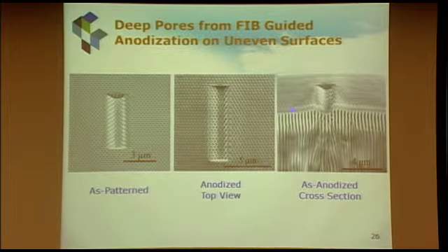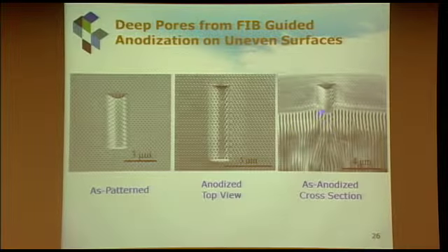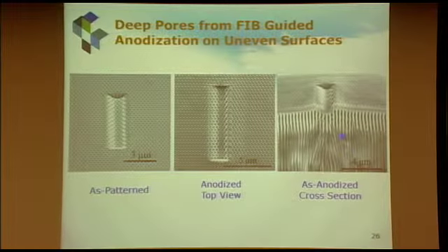So we kind of know what we should do if we run into a situation like this, how to make the pores arrange. But eventually, if you have this concave surface, pores start to split. The individual pore doesn't split, but actually it's a distribution of pores. You start getting new pores through the center. So this image we did through the FIB cutting process, you see some of the defects.